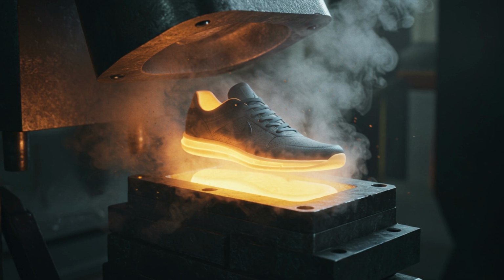After a few minutes of heating, the chemical cross-linking is complete and the blowing agent has fully reacted. The machine then releases the hydraulic locks and the mold pulls apart. In a fraction of a second, the atmospheric pressure drops. The dissolved nitrogen gas inside the EVA instantly seeks to escape, but it's trapped within the cross-linked polymer chains. The result? The entire midsole spontaneously expands, literally jumping out of the mold.